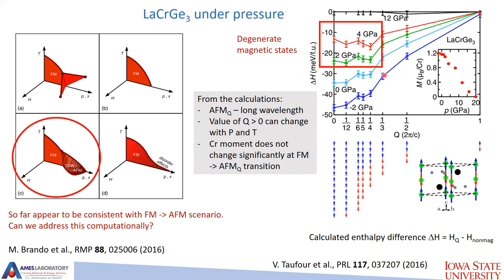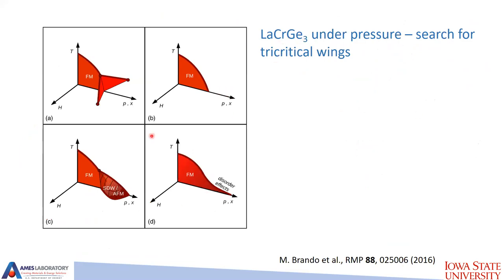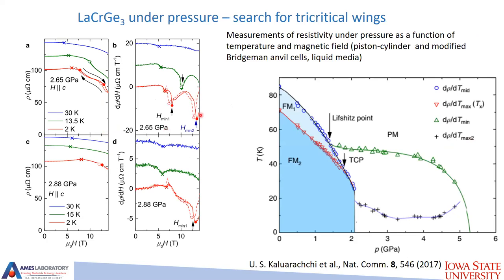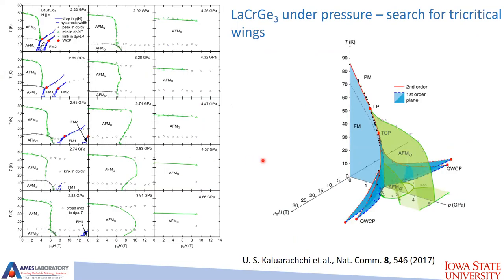Fine, so far, so good. To go even further, we can check if there are the tricritical wings which exist for this material. You do the same thing, but add another variable, magnetic field, and follow resistance, or better, the derivative of resistance, at different pressure and temperature points. You end up with multiple HT phase diagrams, part of them shown here. You can put them together on a three-dimensional plot, and that's what you will get.